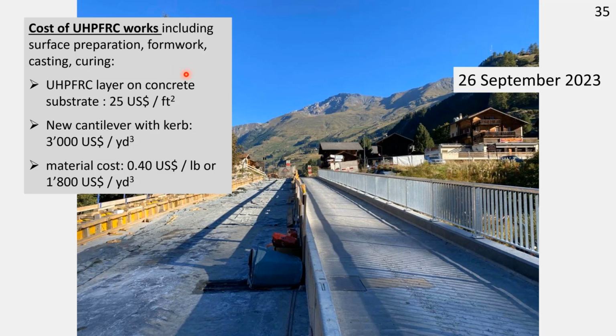That's always a tricky issue. And please keep in mind that the level of cost, or the cost of living in Switzerland, is quite different to the one you know in the US. But the prices are as follows. For the UHPFRC layer on the concrete substrate of a thickness of roughly 2 inches in average, this costs $25 per square foot. Now, the massive concrete on the formwork of the cantilever slab is about $3,000 per cubic yard. And this includes, of course, the surface preparation of the slab, hydrodemolition, the formwork for the cantilever slab, the casting, curing, everything that goes with it.